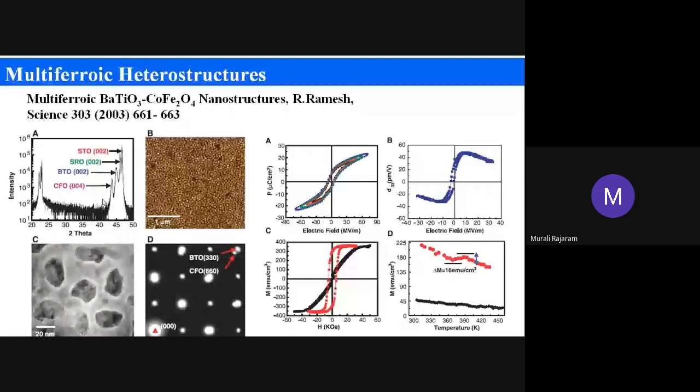And this shows the morphology of the film, and it has quite a lot of nanostructures, particularly aligned nanostructures on the top surface. An AFM image of that one. So this is the TEM image. So you can clearly see the spinels here, cobalt ferrite spinels, which are arranged as rods in a barium titanate matrix. On a TEM image, you can clearly see spots of barium titanate and cobalt ferrite. So this implies these are all single crystalline, highly pure thin films.